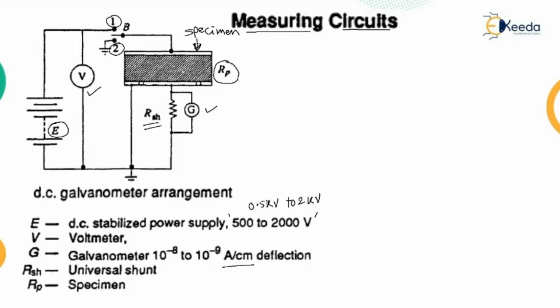So now let us understand this circuit. A simple measuring circuit for the measurement of resistance is shown in the figure. The galvanometer is first calibrated by using a standard resistance of 1 to 10 megaohms. So your first step is to calibrate the galvanometer with 1 to 10 megaohm, with an accuracy of say plus minus 0.5% or plus minus 1%. Now, if necessary, a standard universal shunt is used with the galvanometer, connected across the galvanometer. The deflection in centimeter per microampere of current is noted.